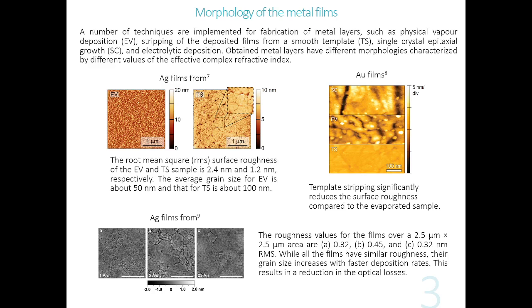When we talk about surface plasmons, which is the case for biosensors, we have to think about the fabrication of thin metal films. There are some techniques to do it. It's a simple evaporation method, and the evaporation and template stripping method, which is characterized by higher quality films in terms of grain sizes and smoother surfaces in comparison with evaporated films, and the single crystalline growth method to get metal films, which allows to get high quality films.